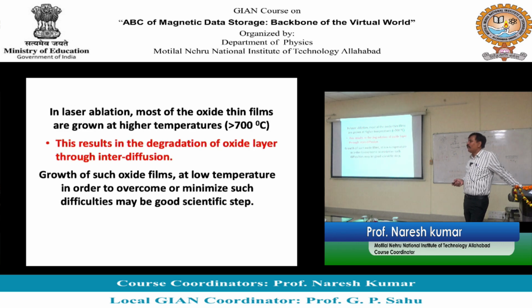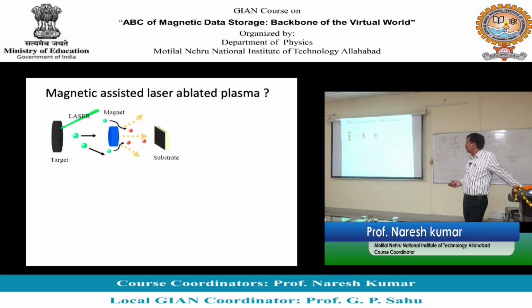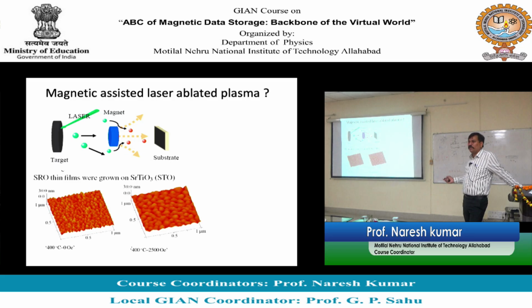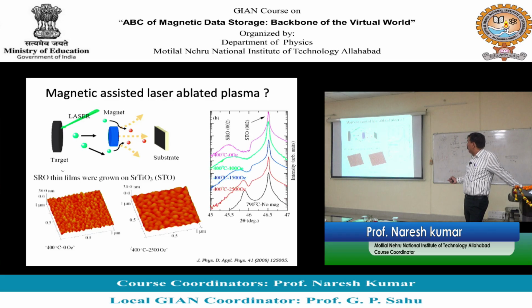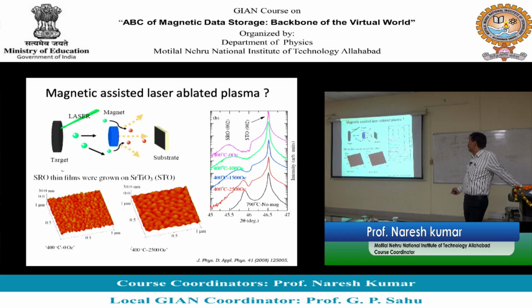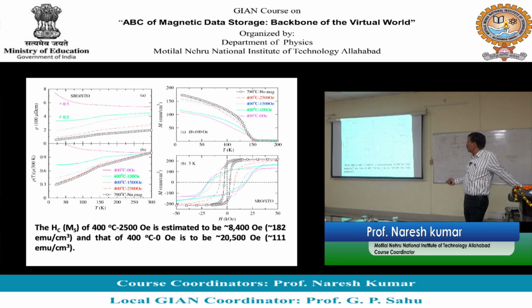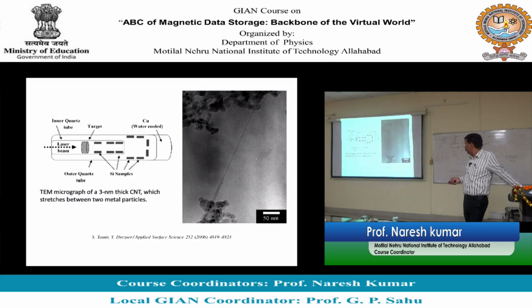One more issue in thin films by PLD is that growth temperature is an issue. It is grown at very high temperature. So what has been done? We placed one permanent magnet in between. This provided some additional energy so that you could lower the growth temperature. For strontium ruthenium oxide, we could grow these films on STO substrate at a very low temperature of 400. Otherwise, we were growing the same film at about 800 degrees centigrade. So we could reduce the substrate temperature by 50%, and properties were almost the same as the films grown at high temperature. All transport properties, magnetic properties, and TC came out the same.